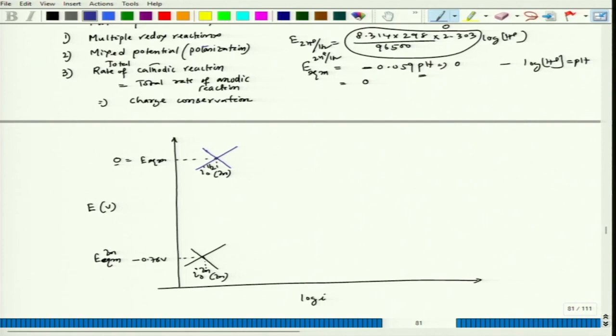And in order to maintain that mixed potential, again, I'm requesting whoever wants to understand this mixed potential, please go back and see the earlier lecture series. So, they will try to achieve a potential by extension of the anodic part and extension of the cathodic part. So, here they will meet, and this point will be the E mix, or it can be called E corrosion, fine. And at that time this particular current density corresponds to I corr.